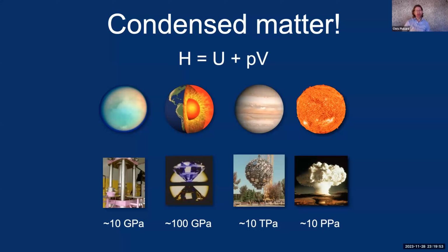So when you're doing high pressure calculations, compared to the challenges of the experiments, which are shown at the bottom, ranging from a large anvil press to a diamond anvil cell to the National Ignition Facility in Lawrence Livermore, or even atomic explosions to generate extremely high pressures, from a computational point of view, all we have to do is, instead of minimizing the internal energy U, we minimize the enthalpy, which is U plus the pressure times the volume. And I think of this as a penalty function against volume. So this is an optimization which is penalizing structures with high volume, and the degree of penalty is determined by this pressure P.